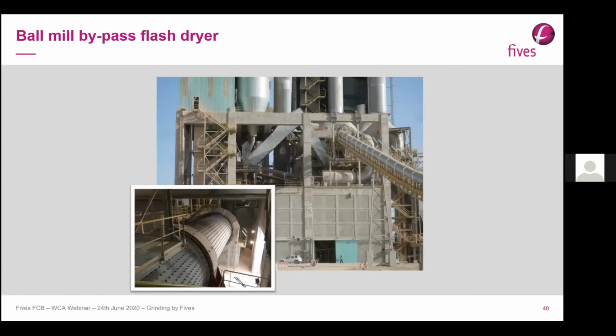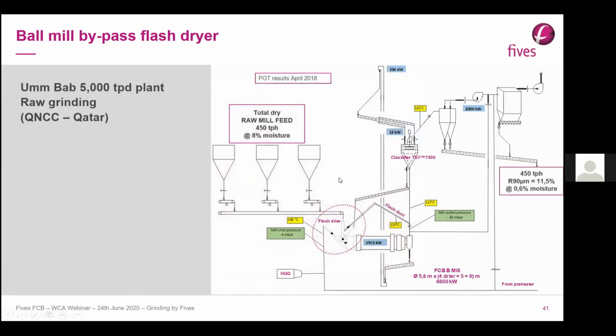One recent example is in Qatar, a raw mill plant, 450 tons per hour. The mill is 5.6 meters in diameter, with installed power of 6,600 kilowatt. And you can see on the first floors the inverted V, which is the flash duct. Process result, as I told you, is 450 tons per hour at 8% moisture, with only 26 millibar pressure drop of the mill.